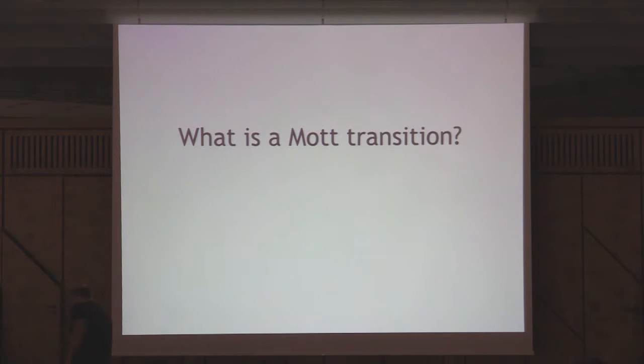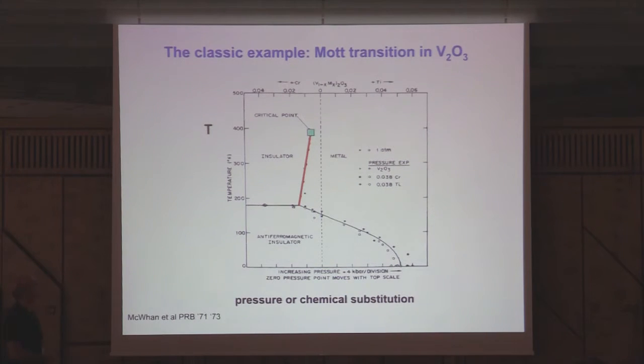The prime example of a Mott transition is found in V2O3, and basically it is a compound where naively you just do the electronic counting and you expect it to be a metal. You are less naive, you do a state-of-the-art density functional calculation, and it's still a metal. But you go to the lab, do the experiment, and when you get a good sample, it's an insulator. So this is the case in V2O3, where you expect a metal, but it is an insulator.